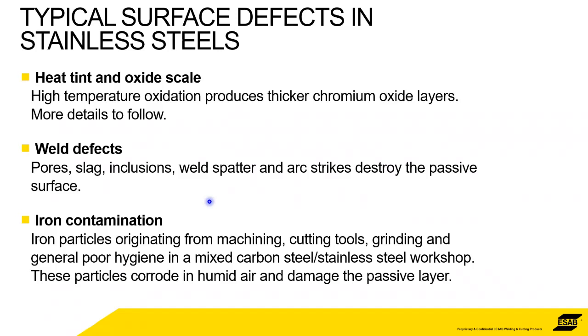Poor hygiene is a favourite as well for fabricators of stainless steel. If you have a shop that's fabricating carbon steel in the same shop that's fabricating stainless steel, then the use of the tools, whether it's brushes or grinders, shot blasters, whatever, if you're using those tools on the carbon steel and then use them on the stainless, then you're going to get contamination of the stainless with carbon steel. So you're going to put particles of carbon steel on the stainless, and that's going to get rid of the passive chromium oxide layer.